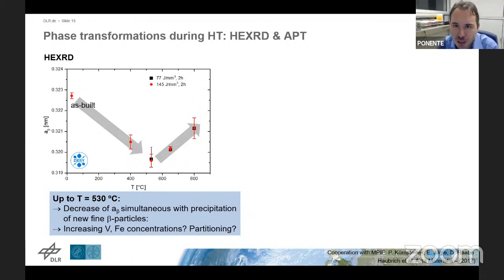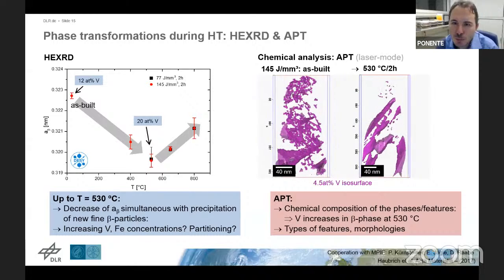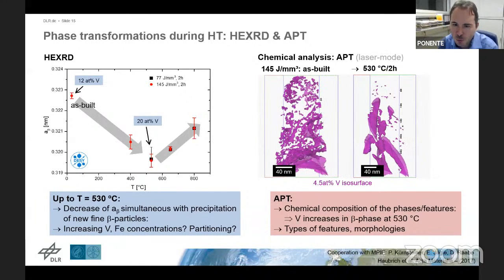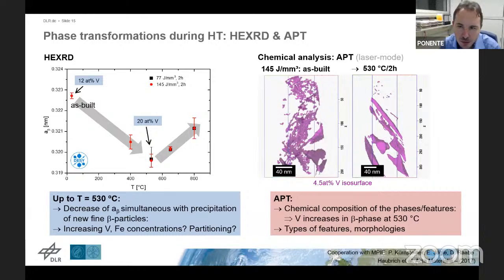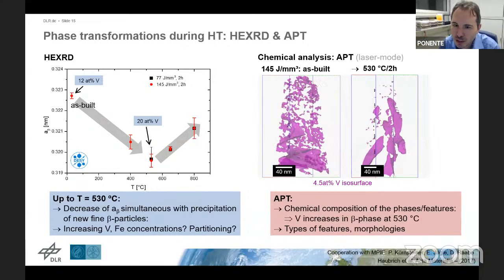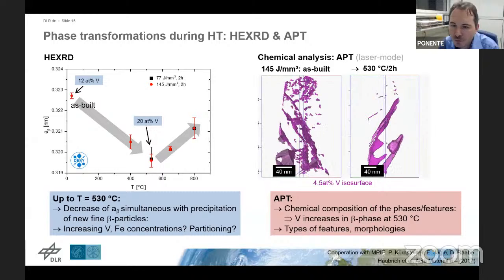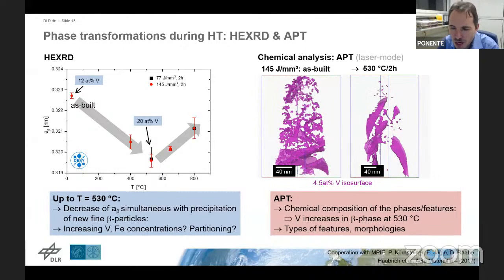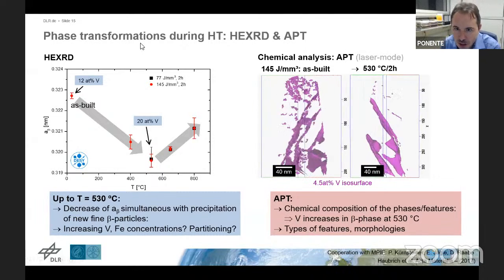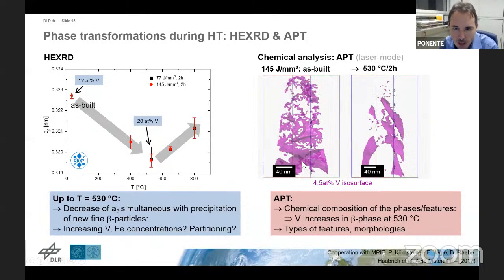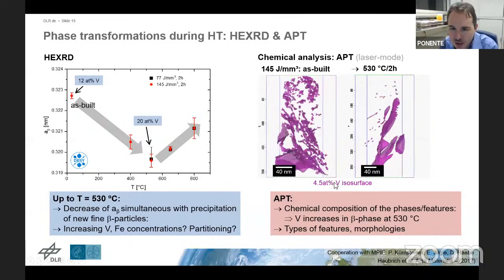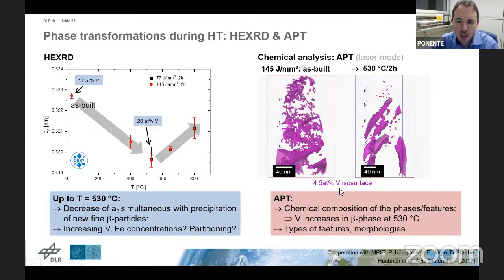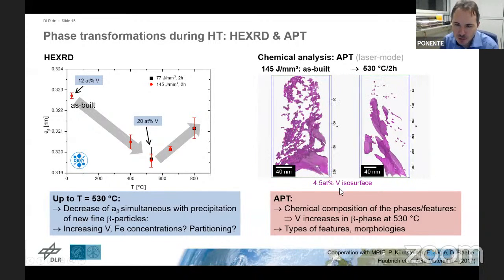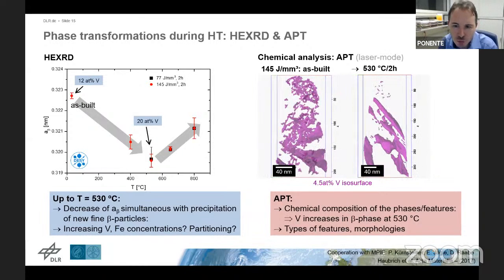In order to further understand that, we had a cooperation with the colleagues of the Max Planck Institute in Düsseldorf nearby, who did atom probe tomography. So it's a tomography used chemically, using a mass spectrometer essentially for detection of single atoms with very, very small samples, but very high sensitivity. And this, for instance, allows us on the right-hand side to characterize the shapes of the beta phase more. Shown here is an isosurface of vanadium, basically a surface that envelops the regions that are particularly enriched in vanadium.